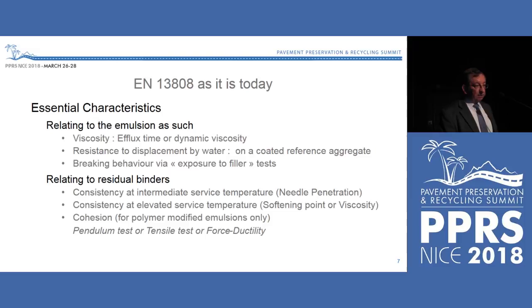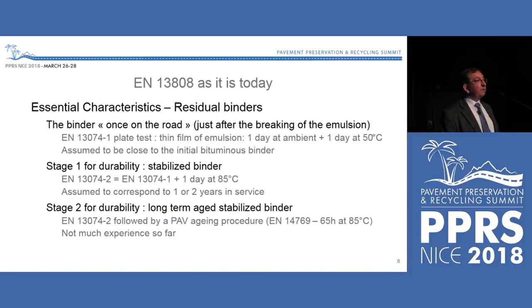Some of them relate to the emulsion as such, like viscosity or breaking behavior, or the so-called filler tests. Most of them relate then to residual binders, and it's mainly requirements on consistency in relation to temperature, and also cohesion for polymer-modified binders. Nevertheless, there is a refinement in the sense that these residual binders are to be considered at different stages of the emulsion life. The first one being, of course, the product once it's on the road.